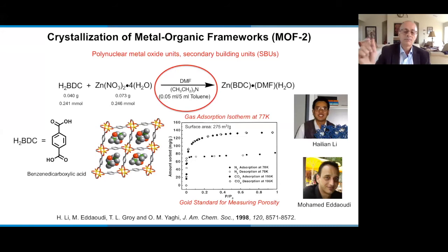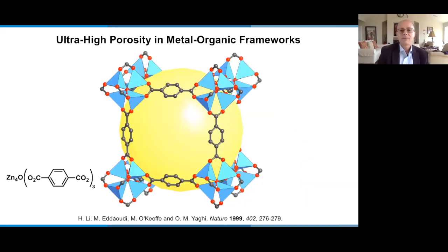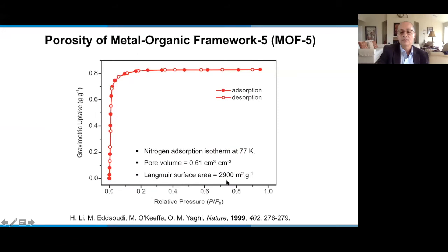So strong bonds and these polynuclear building units, or the SBUs, are absolutely essential in building a robust architecture. Well, when we reported MOF-5, which was made from, instead of a dinuclear building unit, now a tetrametallic unit linked together, as you see here, with a charged linker to make an extended primitive cubic structure. This had a surface area of 2,900 square meters per gram, which we reported back in '99. This was really a breakthrough because it broke all records of porosity, and it showed that our idea of the polynuclear SBUs to produce rigid structures that have permanent porosity can be extended to other building units.